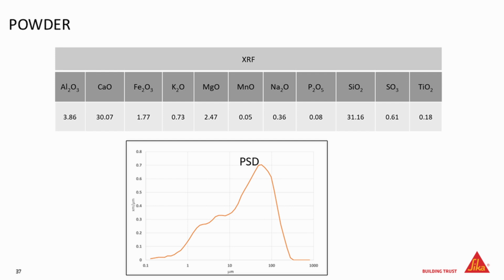What we use as a calcium source is limestone, calcium carbonate, and then by heating it up, you separate the CO2 from the calcium carbonate, so you come to calcium oxide. Here you have calcium oxide directly as a source. So you don't need to separate the CO2 in the kiln, and that chemical decomposition of the limestone is roughly 50% of the CO2 output of cement production. So this could also be an interesting use of the powder. Of course, here we have to discuss the amount of powder that is available. That is another discussion, but this is a possible use next to the use as filler material.